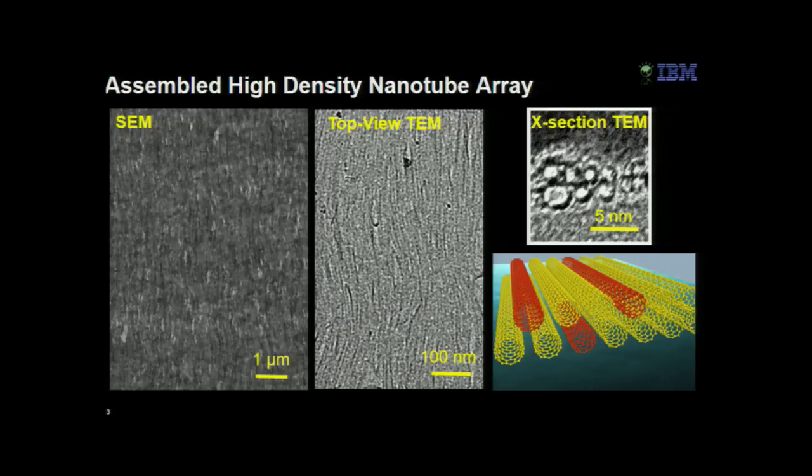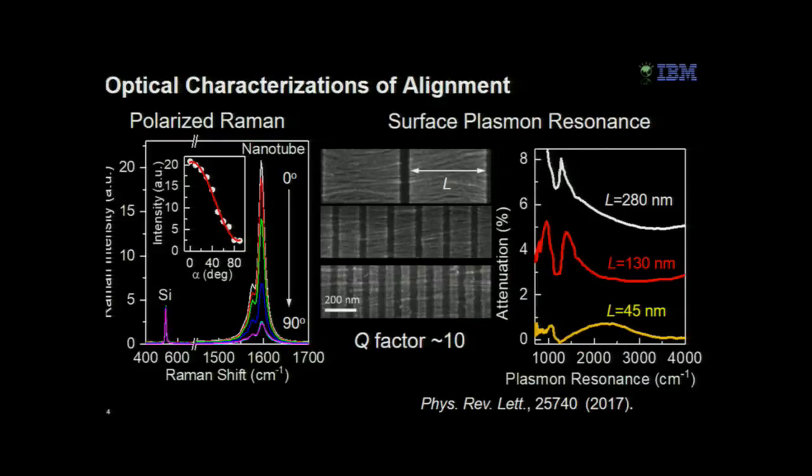And since the nanotube pitch is self-limited by the nanotube diameter, these aligned arrays fully cover the wafer surface with density above 500 nanotubes per micron, as characterized by both top-view and cross-sectional TEM. The good alignment quality is also confirmed optically with polarized Raman spectroscopy. The nanotube Raman signal is greatly reduced if the polarization direction of the incident laser is perpendicular to the nanotube alignment direction. It is also reflected in the unprecedentedly high quality factor for a surface plasmon resonator made on aligned arrays of carbon nanotubes